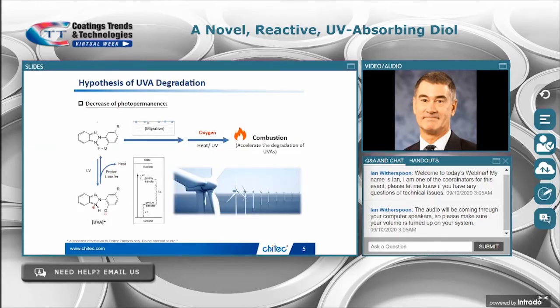First I want to show in normal UV activity, we have this cycle between excited state and ground state, and it should go back and forth. But if you've got the migration, then you get loss through oxidation up here. Materials on the surface can get exposed to more free radicals, dirt, rain, pollen, and so forth, and then they degrade or are lost quicker. And of course, sublimation is a big problem as well. So loss rates for the smaller UVAs can even be exceedingly high. So we really need to figure out how to minimize the migration.